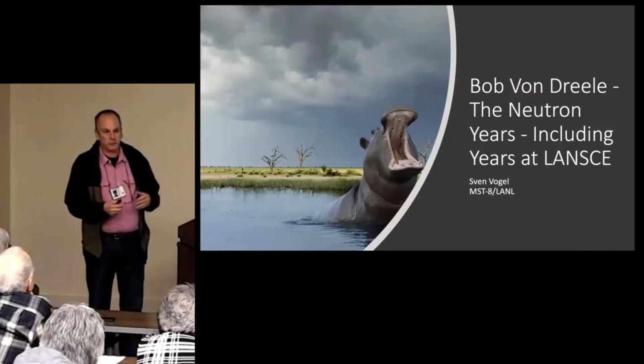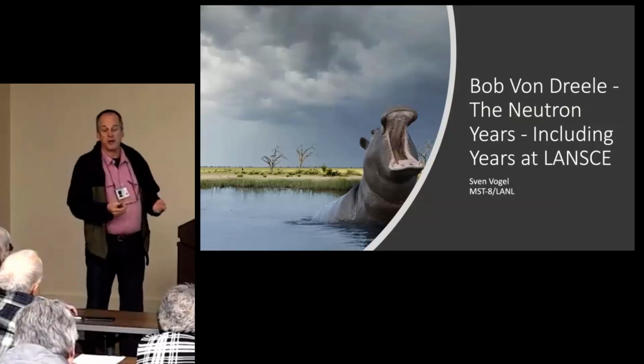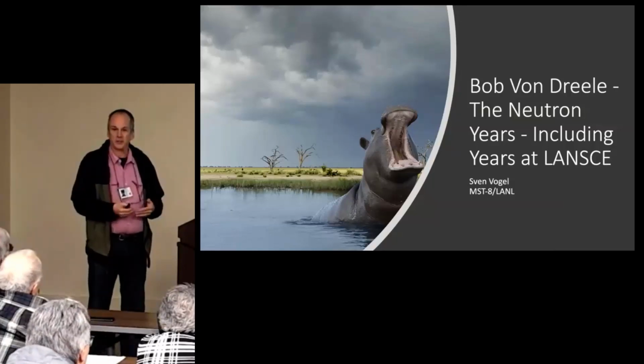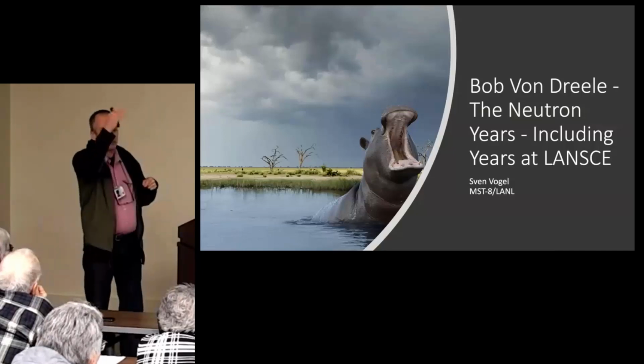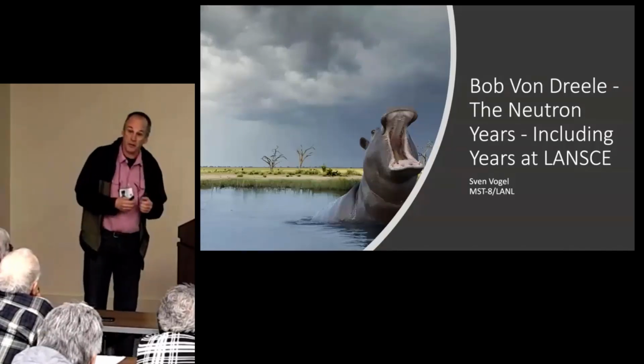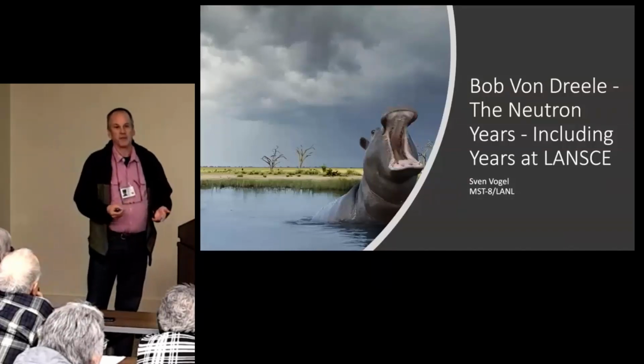I came to Los Alamos to look at neutron transmission, which is the leftover after all the diffracted neutrons are out of the transmitted beam. You're left with what's called Bragg edges, right? When Bragg's law, sine theta, reaches 1 in the transmitted signal, you get a steep increase. That's called a Bragg edge.